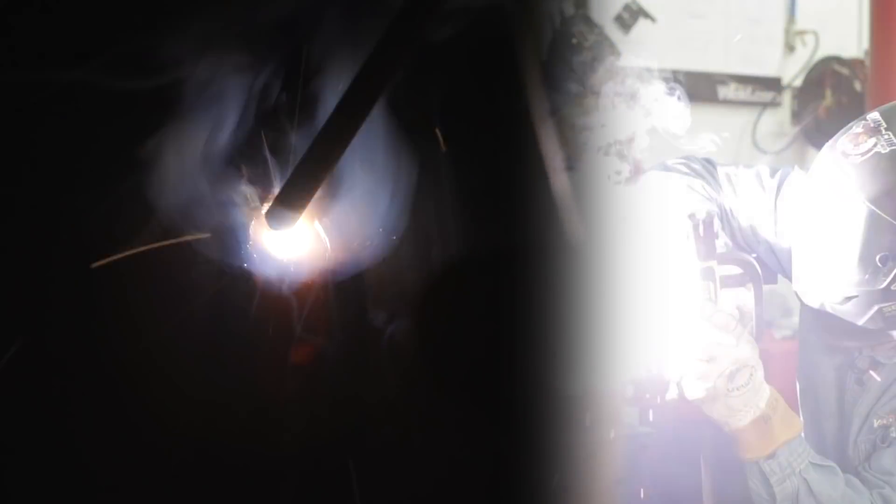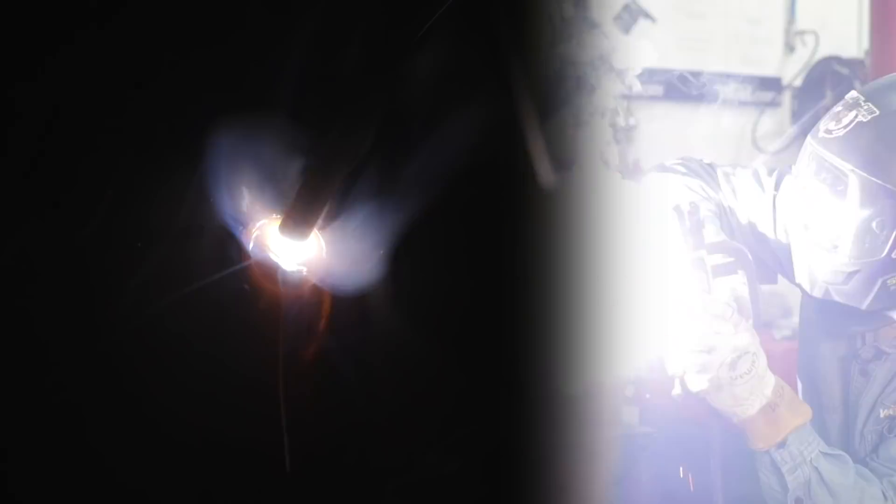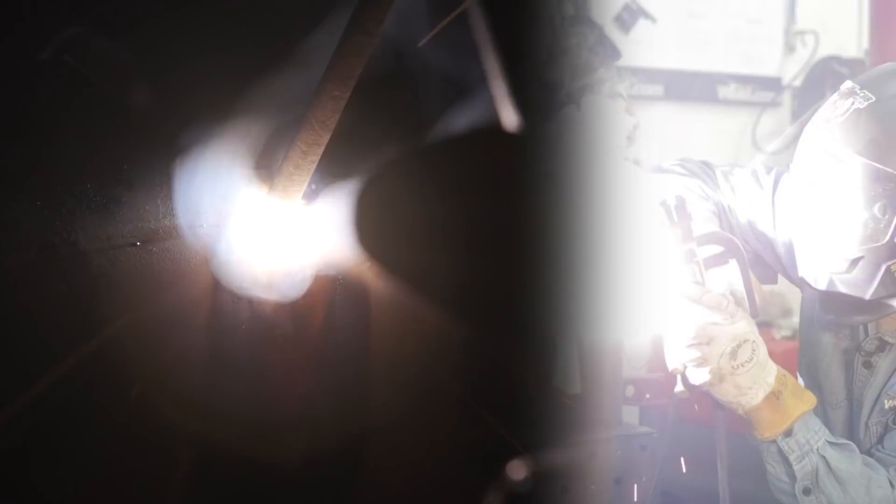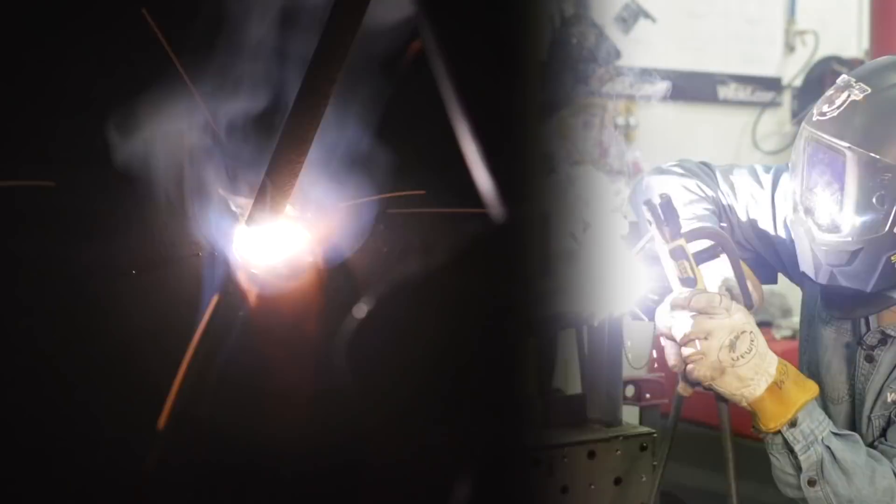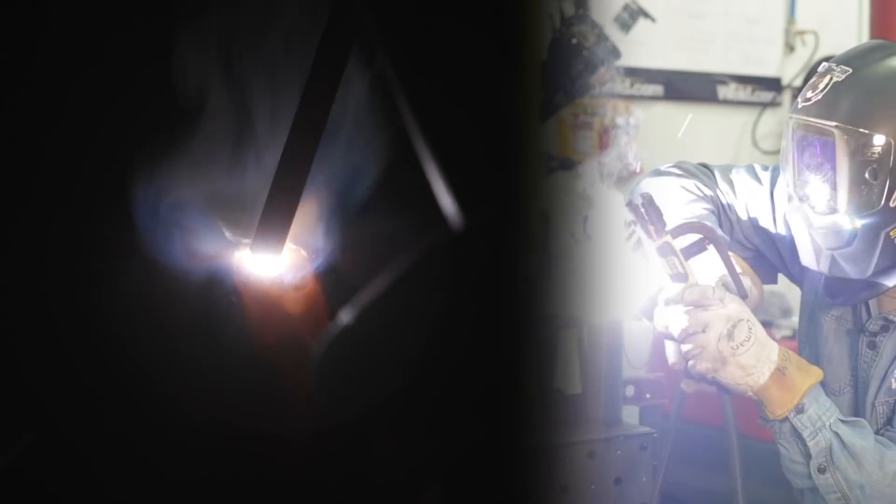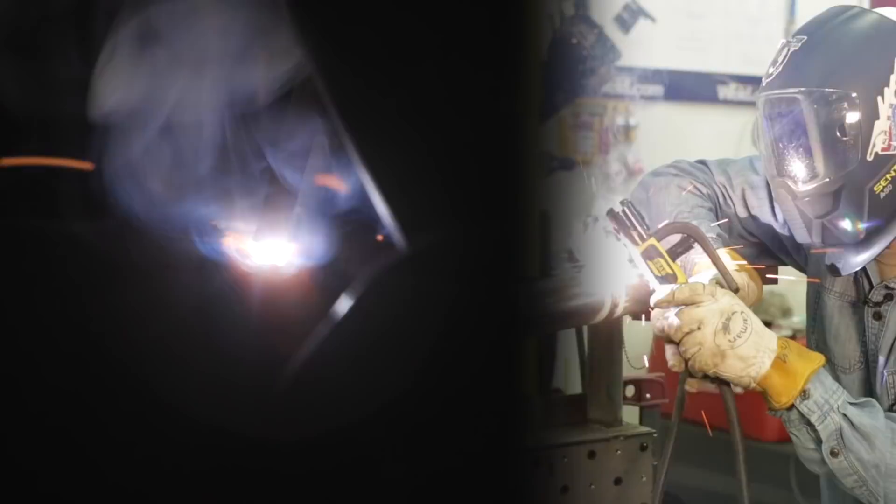This technique that I'm going to use is pretty much stay right in the pool all the time. Weave this back and forth very slightly. I'm watching the edges. I want to establish this crown or reinforcement no higher than an eighth. I'm going to run out of rod.